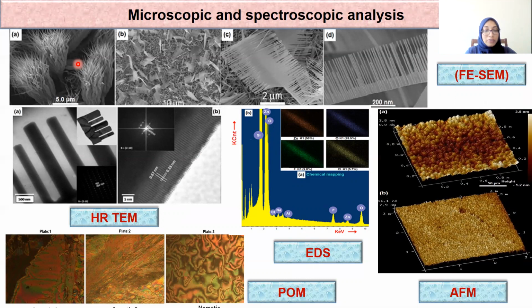The close examination of this figure also reveals that the nanoflower morphology is formed by the aggregation of multiple one-dimensional zinc oxide nanospikes. You can see that the nanospikes emerge radially from a central source in such a way that they create a flower-like morphology. And it is also found that the nanoflowers do not possess uniform diameter.